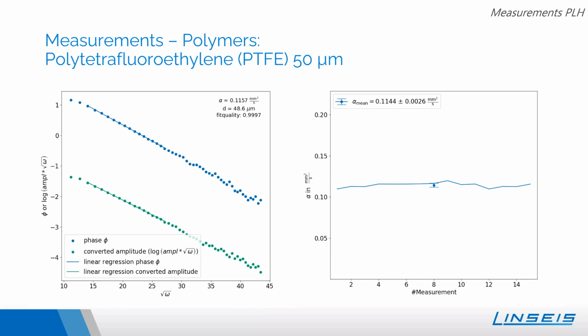So as you see here, as an example, polytetrafluoroethylene again, with a thickness of 50 micrometer, and the expected value for the thermal diffusivity of Teflon is 0.11 millimeters squared per second. As you can see, our measurement yields exactly this value, and the repetition of the measurement reproduces this value very precisely. So it's a very nice measurement.